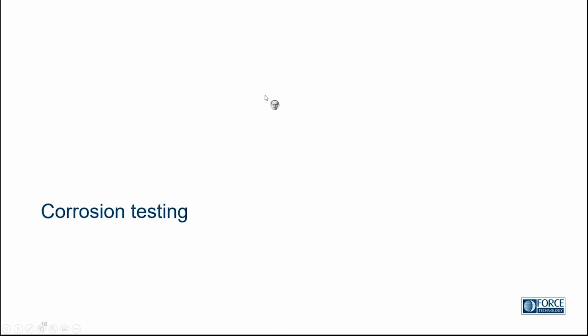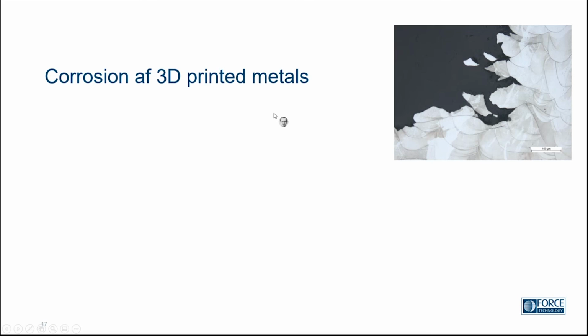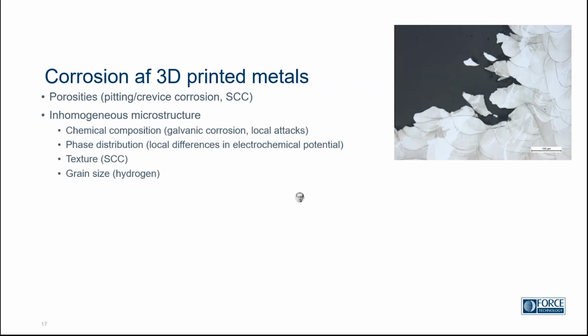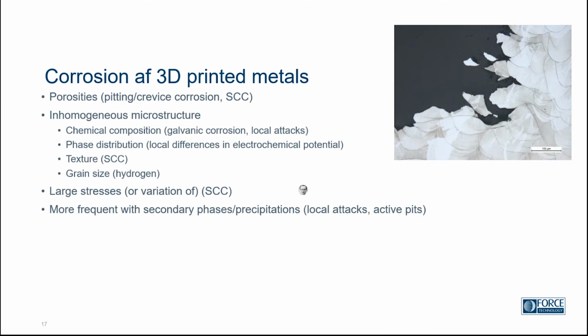So when we talk about corrosion, corrosion of 3D printed metals happens by the same mechanics that you will have with normal steels. The only difference is that you may have a more inhomogeneous structure, which, depending on your control of your print parameters and the quality of your product, can be more or less. And then the heating and cooling will impose some stresses into the material, and whether that's a problem or not is again something you need to look at.